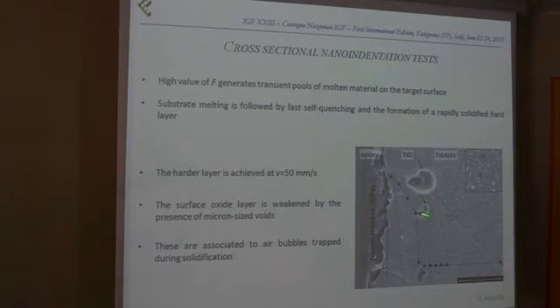Also, as you can see here, we had voids created by the process itself, because at the lowest speed and at the highest fluence we had a very rapid increase of the temperature of the surface, and the air was acting like a self-quenching. So basically the air bubbles were trapped during the solidification stage, and this particular layer was, according to our ideas, a weak layer. So we didn't bond the sample for this case.